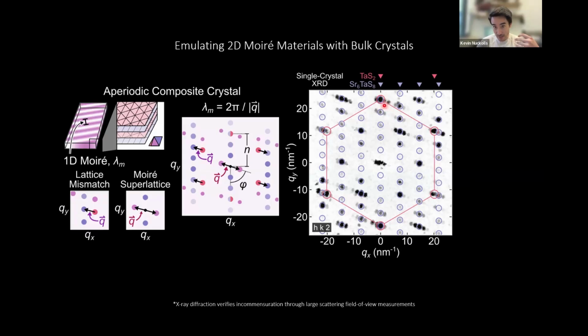So the first is that these red circled peaks in the diffraction pattern are six-fold symmetric, and so they have to be associated with a hexagonal sublattice. Whereas these blue peaks right here are twofold symmetric, and I can identify a monoclinic angle in the diffraction pattern. So they have to be associated with monoclinic layers. There are actually a lot of other peaks in this diffraction pattern that are unassociated with the individual layers, and it's hard to know what these come from without a higher resolution probe.